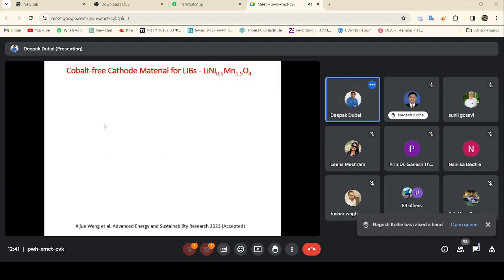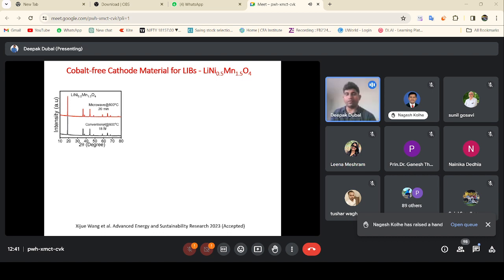So one of my PhD students, Rebecca, tried to synthesize the cobalt-free cathode material. The reason a lot of industries and researchers are interested in manufacturing cobalt-free cathode material is because cobalt is a very expensive mineral, and that has only been available in the Republic of Congo. So that's the only country that mines the cobalt. So we recently developed this very high capacity cathode material, which is without cobalt, so lithium nickel manganese oxide.